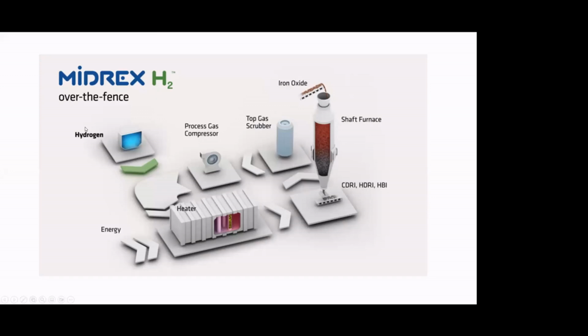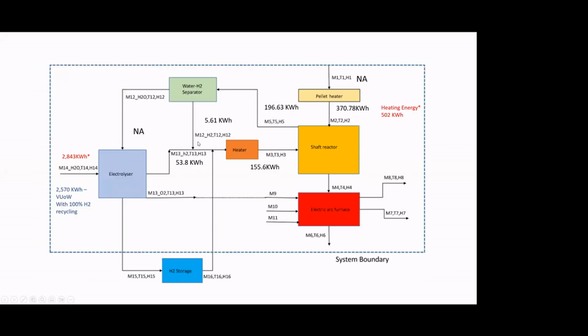So if you're Midrex, you put out a very attractive looking process diagram, with the hydrogen, the heater, heating up the pellets and so forth. In reality, the process looks more like this, and it is mostly characterized by the kilowatt hours used to create the heat, to create the hydrogen, to heat the pellets up here, heat the hydrogen, and then recover the hydrogen afterwards.